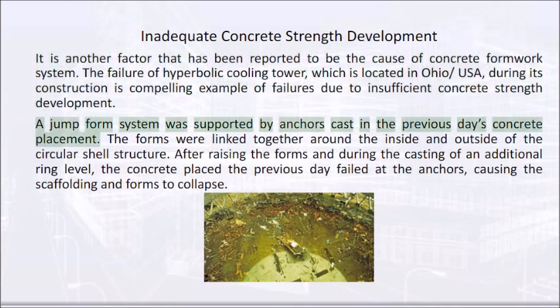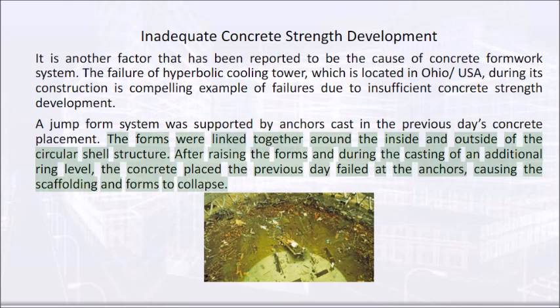A jump form system was supported by anchors cast in the previous day's concrete placement. The forms were linked together around the inside and outside of the circular shell structure. After raising the forms and during the casting of an additional ring level, the concrete placed the previous day failed at the anchors, causing the scaffolding and forms to collapse.